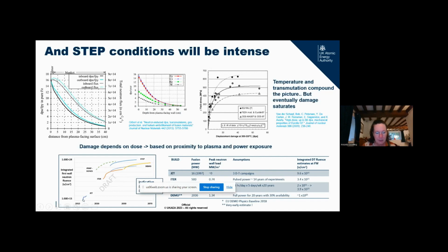But if we think JET has been built in recent years, and just looking at the last couple of years on the timeline below, the neutron load, the fluence, the total load on the wall is in the order of 10 to the 15 over here, neutrons per square centimeter. ITER will look to put a load at orders of magnitude higher fluence. And then if we look at the blue lines as the bracket for STEP and eventually DEMO, the European power plant, you can see that we're into a domain of neutron load that is significantly more onerous than what we've ever tested in experiments in real tokamaks to date. And so that is the work, the burden of proof that lies ahead of us.